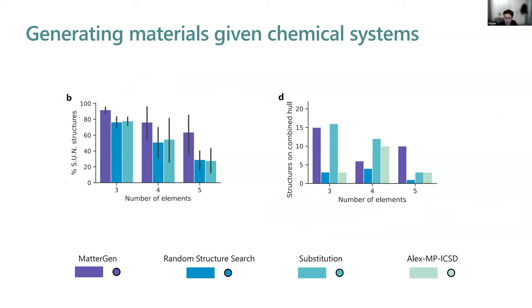This is our result. You can see different colors represent different methods, but our key result is that if you're looking at the structures that are stable, novel, unique, where stable means below 0.1 eV per atom, our model outperforms both random structure search and substitution for ternary, quaternary, and quinary chemical systems.